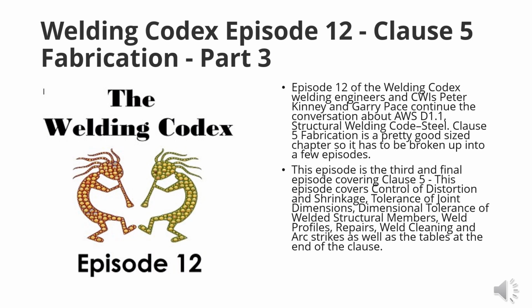If after an unacceptable weld has been made, work performed has rendered it inaccessible or has created a new condition that makes the correction of the unacceptable weld dangerous or ineffectual, then the original condition shall be restored by removing the welds and members or both before the corrections are made. If this is not done, the deficiency shall be compensated for by additional work conforming to an approved revised design. What this basically says is this is going to cost you a lot of money and a lot of time.